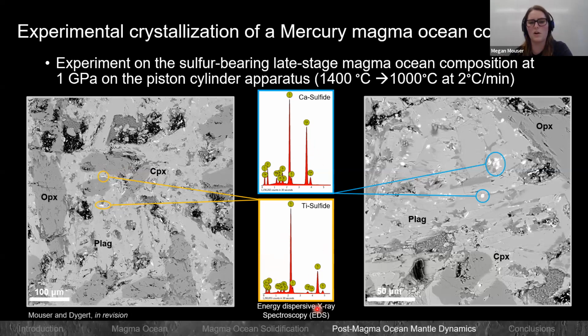And so these spectra here are energy dispersive X-ray spectroscopy. This was done on the scanning electron microscope just to give us an idea of what we're looking at. So it's interesting to see that we have some sort of titanium bearing sulfide. Now it's not exactly a 1-to-1 ratio of titanium and sulfide, but it is interesting that we have a sulfide like this. And this could potentially be a slightly denser sulfide than some of these lighter sulfides that we've been considering. So this is definitely interesting moving forward, and maybe further exploration on the types of sulfides that crystallize in Mercury, I think would be very interesting.